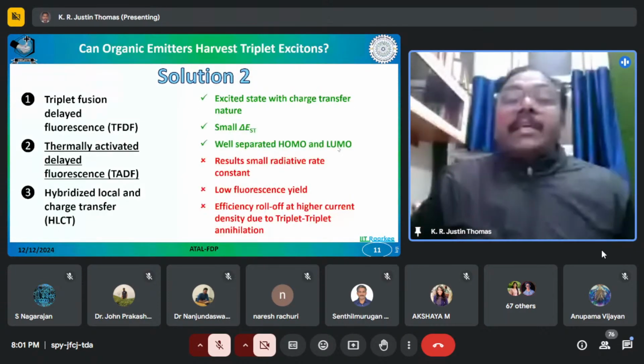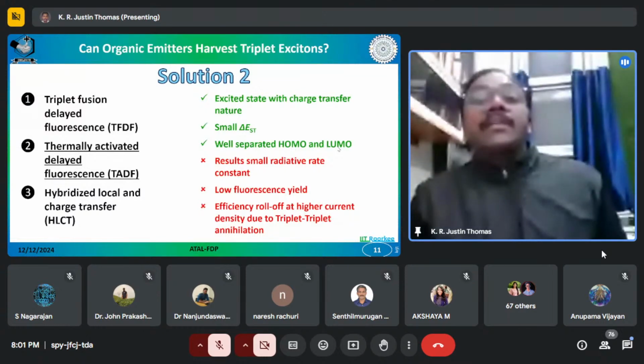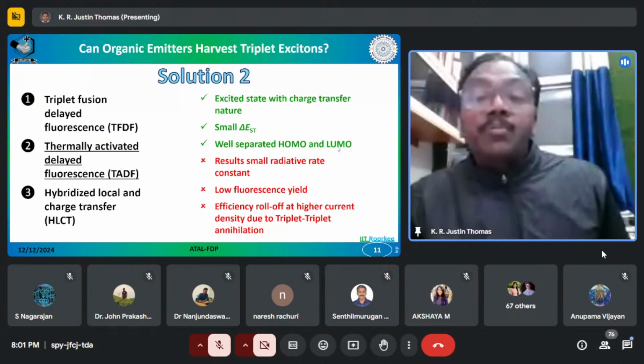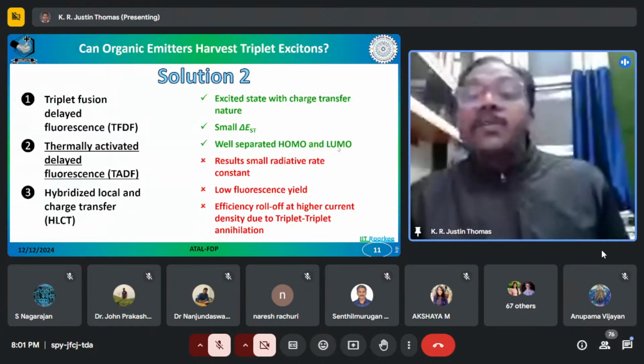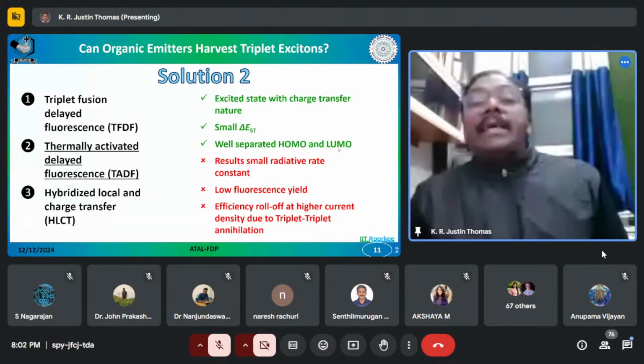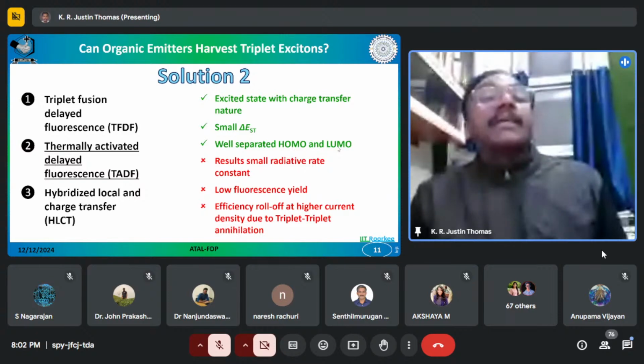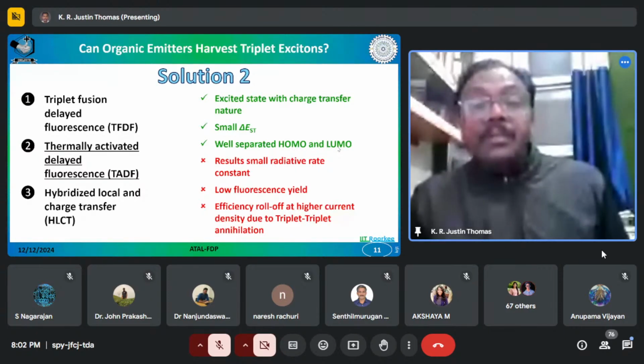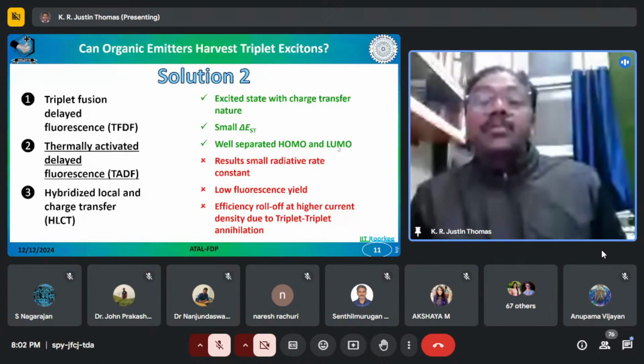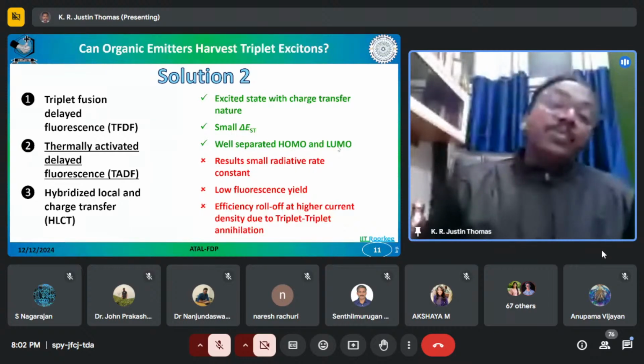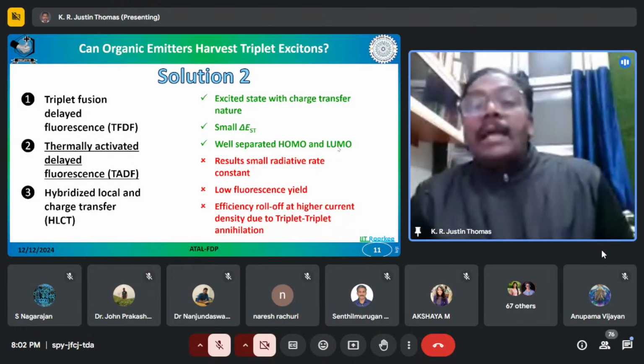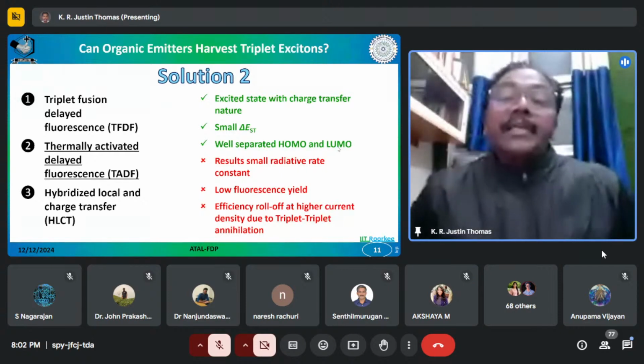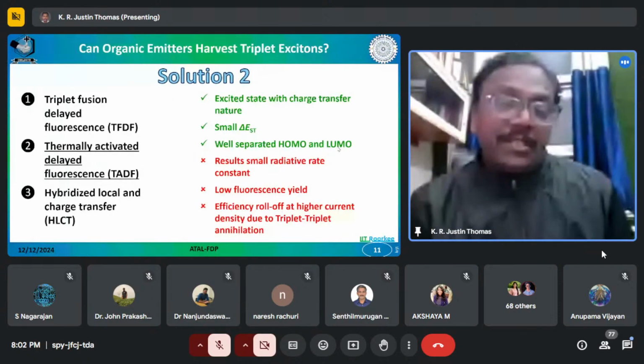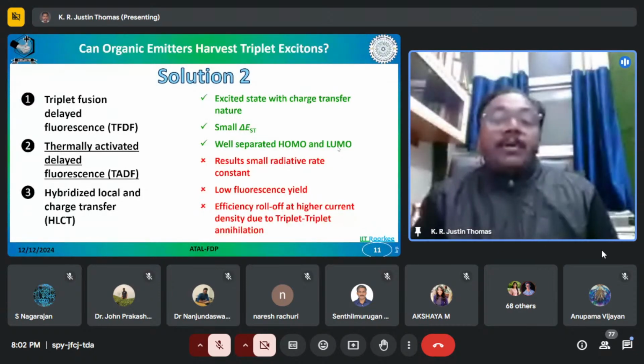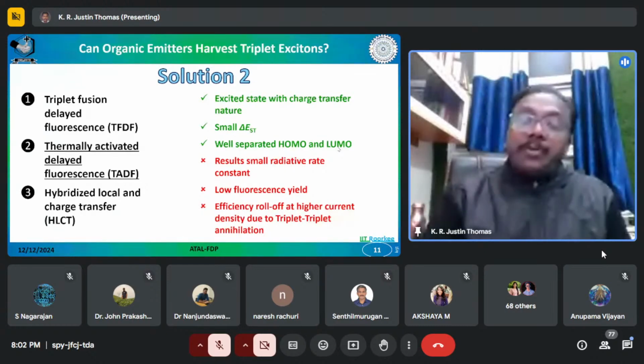Now let's look at the important aspects of TADF. The excited state is charge transfer in nature, as I have told. There will be a small delta EST, arising from the well-separated HOMO and LUMO. The radiative rate constant for these compounds is very low because they are charge transfer in nature, and because of that you will have a low fluorescence quantum yield. And since the SOC is small, at any point of time you will have a large triplet excited state population, which will lead to triplet annihilation, an unwanted wastage of excitons. That is the problem with this, but there are a lot of ways to overcome these problems.